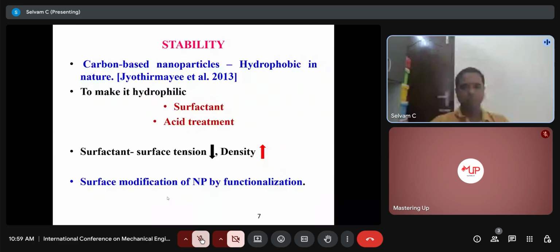with concentrated nitric acid. So the nanoparticles have been taken separately. Initially, in a reflux setup at 400 rpm at 100 degrees Celsius for 2 hours, we treated them with the concentrated nitric acid, and finally after 2 hours it was washed with water and filtered until reaching a pH value of 7. After that, the particles have been dried at 150 degrees Celsius for 6 hours. We can produce the dried, functionalized graphene nanoplatelets or functionalized multi-wall carbon nanotubes.